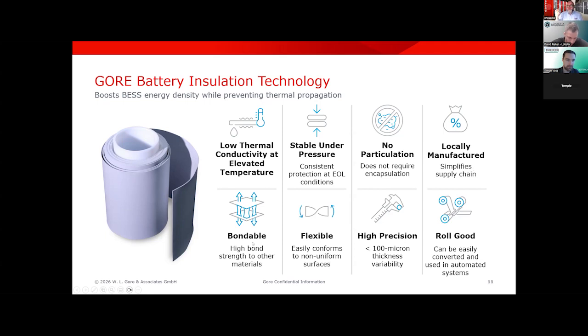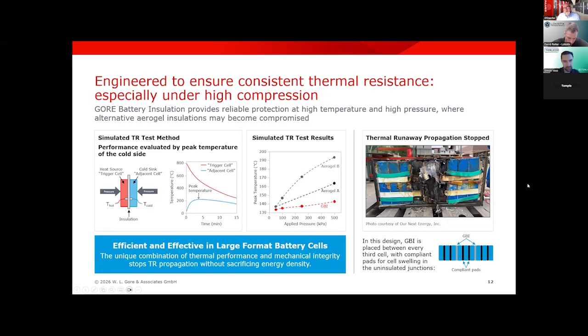So what you could see here, the material is on a reel. It's a soft material. It's a composite out of an expanded polymer and ceramic. You see the flexibility, the highest precision. It's less than 100 micron thickness variability, and you could have it in roll goods for automated production processes. And to bring it to the last point, to compare it, why we believe it's helping to stop the thermal runaway propagation, this material has a different behavior compared to what you're having, for instance, with aerogels.